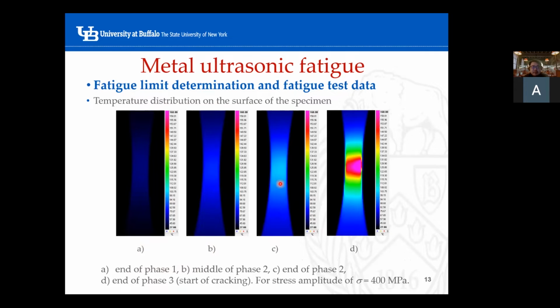We can find that even though in phase 2 the temperature gradient is much lesser than the temperature gradient in phase 3, we still have around 80 to 100 Kelvin temperature difference between the gauge section and the grip section.